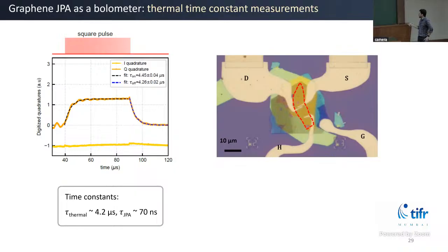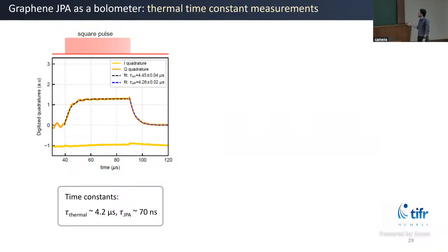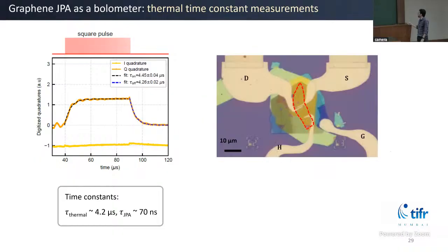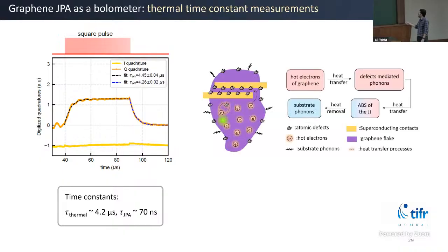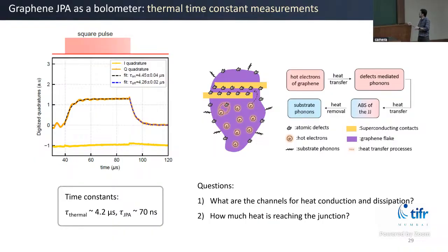And we try to explain that in terms of the heat transfer mechanism of this heated junction. One can be that a hot electron loses heat to another electron and settles down. Another can be that electrons dump heat to substrate phonons. But it turns out in these JJs, the path for hot electrons to go is very narrow here. So you don't have much of a path for the hot electrons to take or remove the heat from the Josephson junction. Rather, as other people have also studied in these devices, you have atomic defects at the edges because you have rough edges that you create by etching the samples. And now there is an interconversion. So the hot electrons dump heat to these atomic defects through a mechanism called defect mediated phonon heat transfer. And from that, the JJ thermalizes to the unheated state.